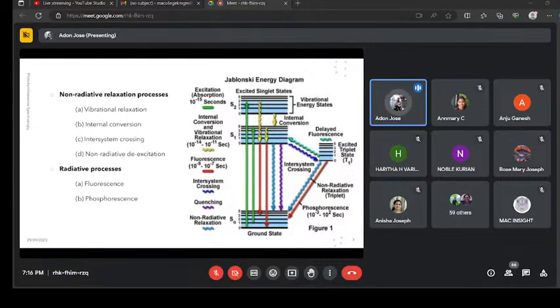The second case is internal conversion. If the molecule is excited to a higher energy excited singlet state than S1, that is S2 here, a rapid non-radiative relaxation usually occurs to the lowest energy singlet excited state. So this relaxation process between electronic states of the same spin multiplicity, S2 and S1, is usually referred to by the term internal conversion. The other term is inter-system crossing, which I already mentioned in the previous slide.